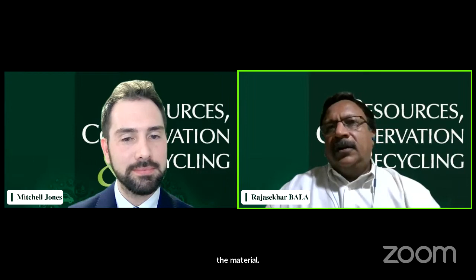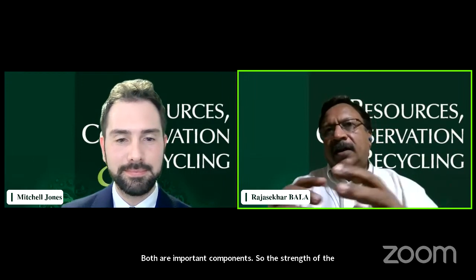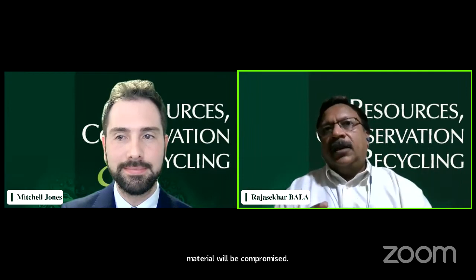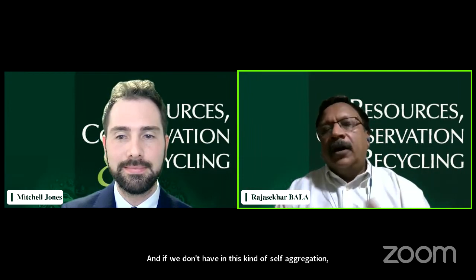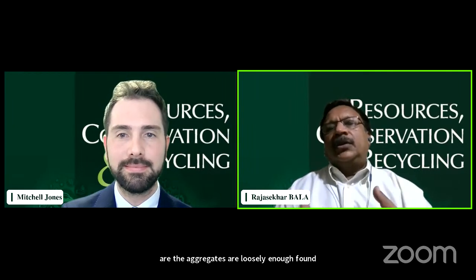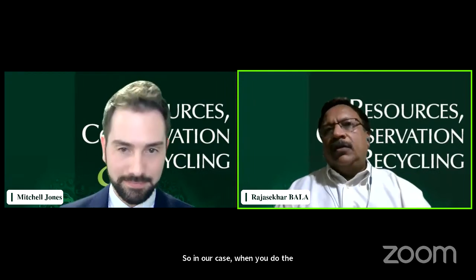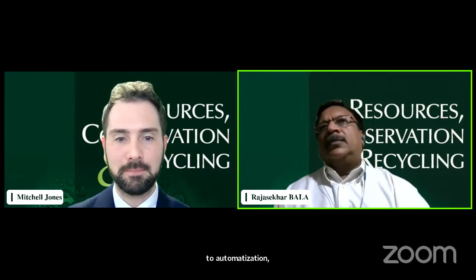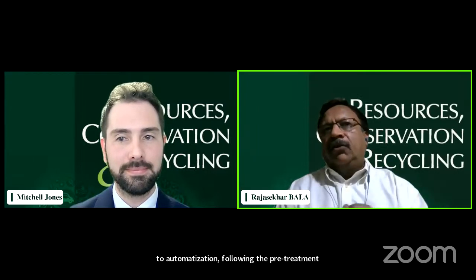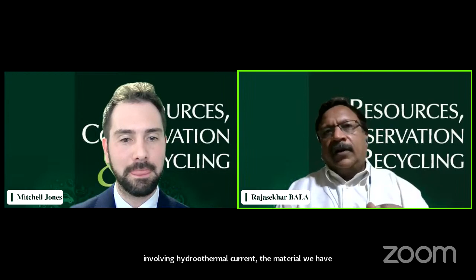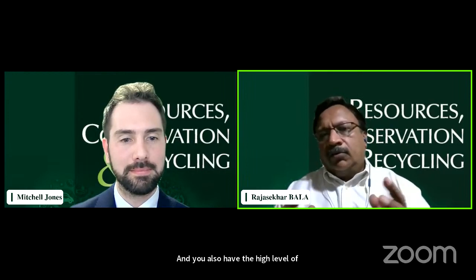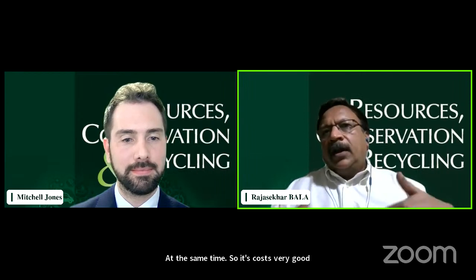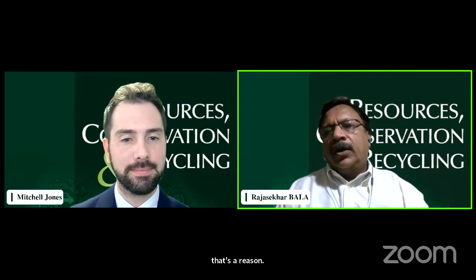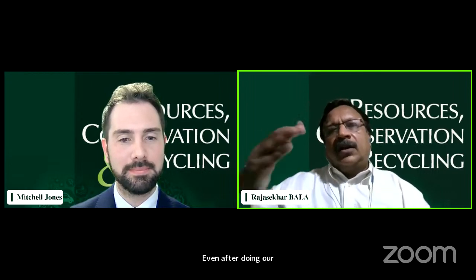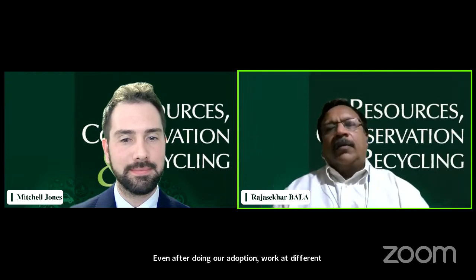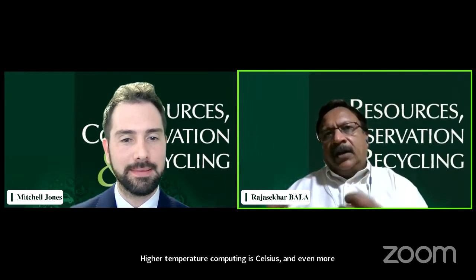So the strength of the material will be compromised if we don't have any kind of self-aggregation, or the aggregates are loosely formed. In our case, when you do the pyrolysis of lignin, through aromatization, following the pre-treatment involving hydrothermal carbonization, the material we have is highly rigid, and it also has a high level of porosity at the same time. So it has very good strength, and that's the reason that even after doing our adsorption work at different temperatures, like 35 degrees Celsius, higher temperature, 50 degrees Celsius, and even more, the material can still be regenerated and can be reused.